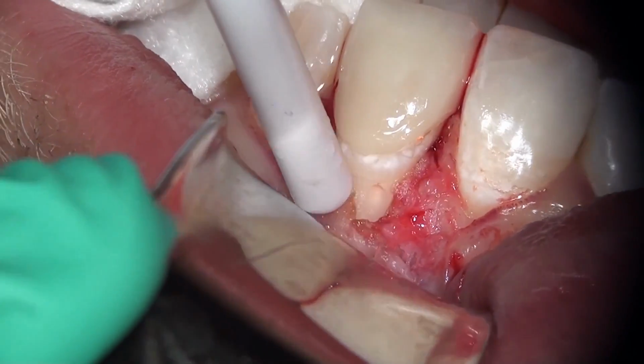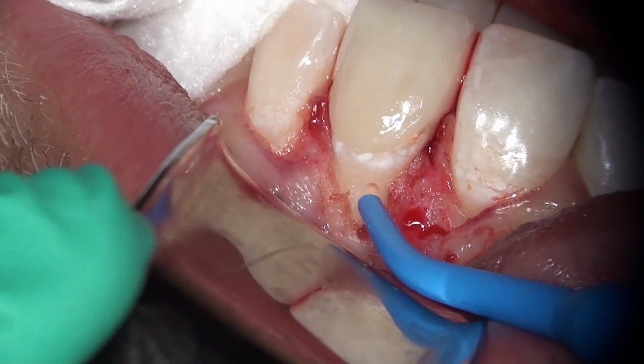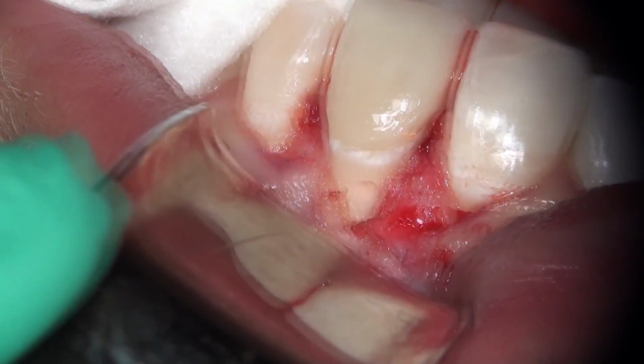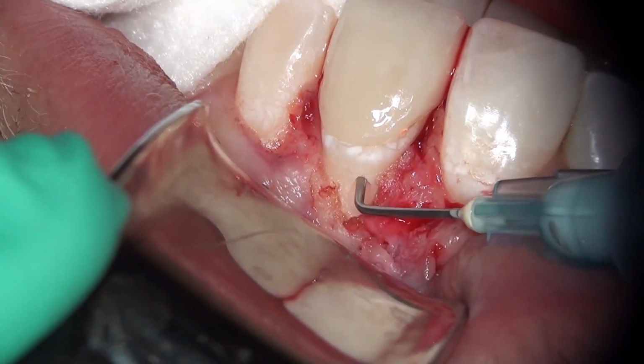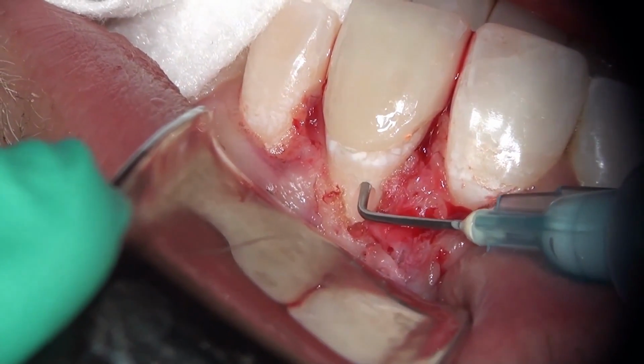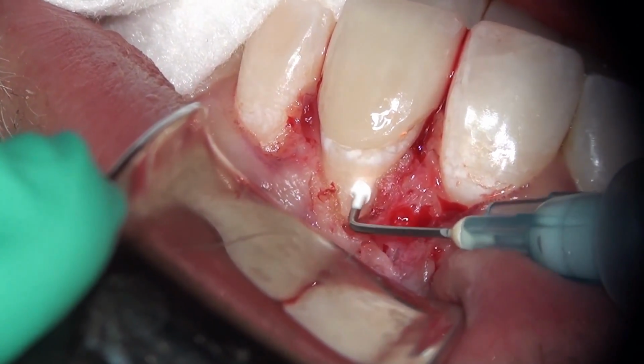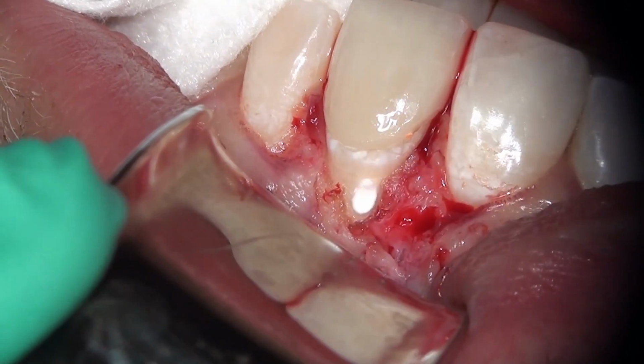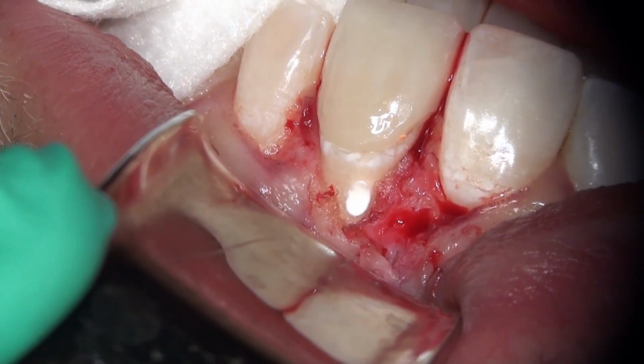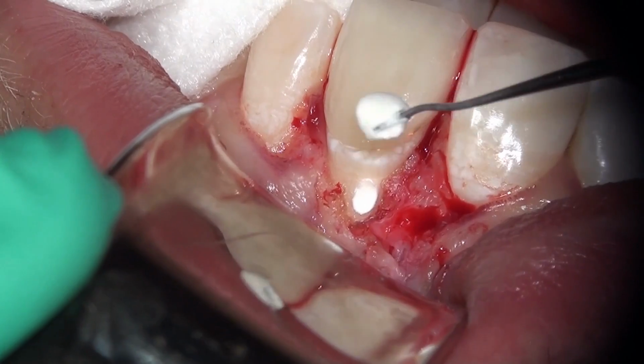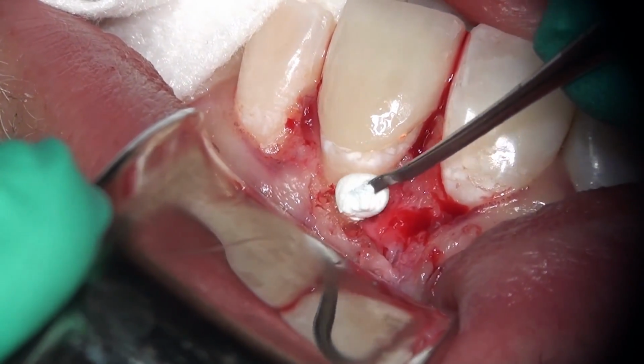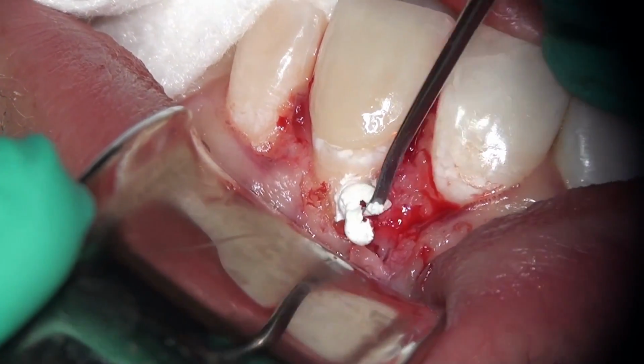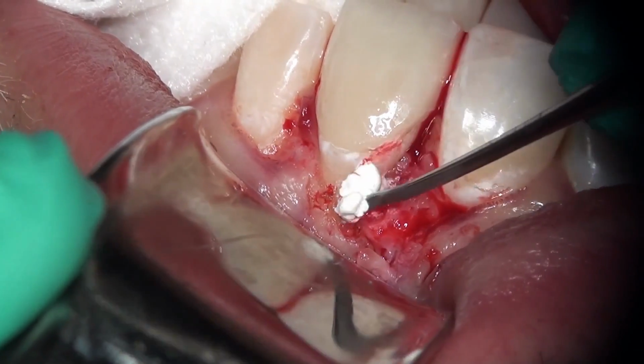Now just washing and drying the site completely. At this point, it's important that when I'm injecting there is no blood. So injecting in and then slowly out, and then placing the putty. Remember, at this point, everything has to be completely dry. But now, once I put the putty in there, a little bit of blood gets in there. It's not as big of a deal because that part is sealed already. So the blood would be basically on top of it.